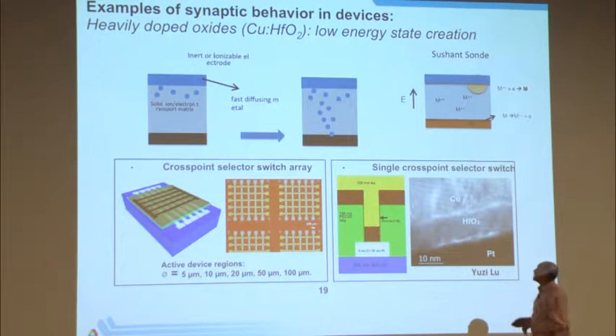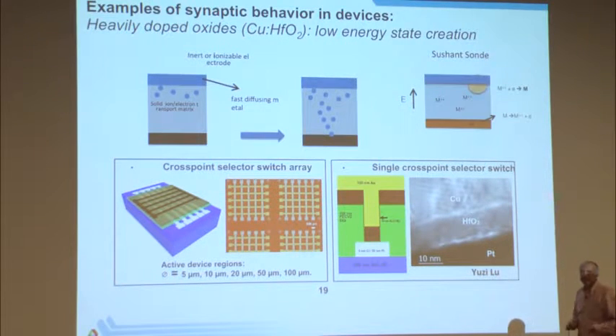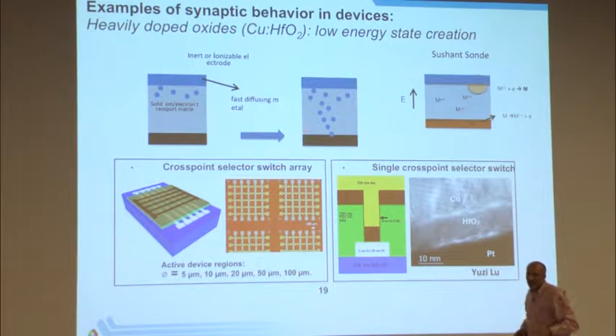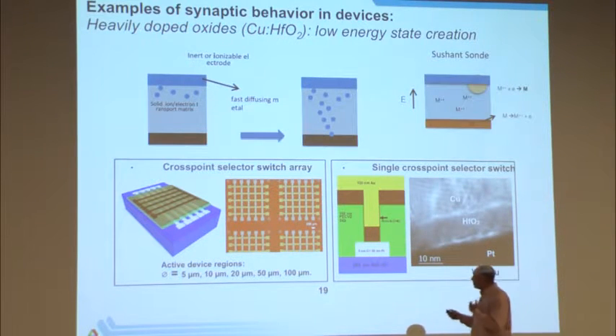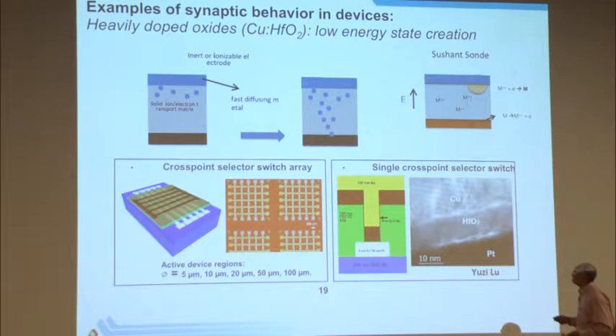The first one is an example of synaptic behavior in a device, and this is work that Sushant Sonde, a postdoctoral scientist and colleague of mine, has been driving. So in this case, we have a platinum electrode, an inert hafnium oxide dielectric, and a copper electrode on top. Copper is a fast diffusing element. The idea is that if you apply a field, this copper somehow forms some kind of filament and its resistive state changes. You can make the device, it's a standard processing that can be done in a clean room, and then you test these devices using what are called crossbar structures.